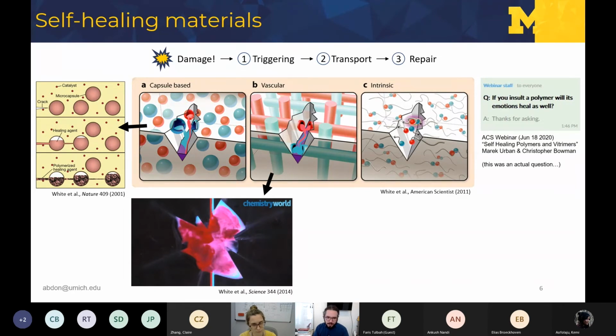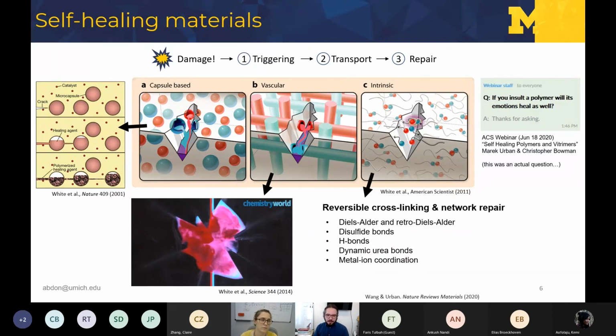and you need to constantly be feeding these healing agents. On the other hand, we have intrinsic healing mechanisms that rely on supramolecular chemistry and on reversible or non-covalent dynamic cross-linking, right? And we're very interested in these types of materials because the network happens at the molecular scale. So you're repairing bonds through different chemistry and different mechanisms, but you can repair very localized small scale damage up to macro scale damage, right? So we're very interested in this latter type of healing strategy.